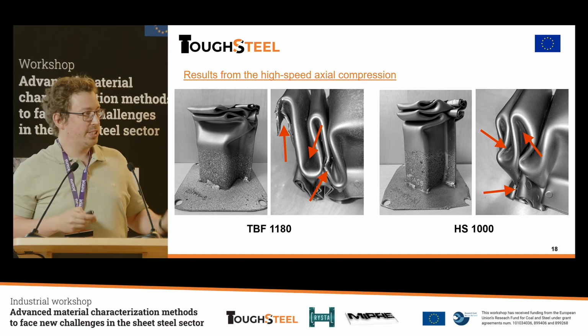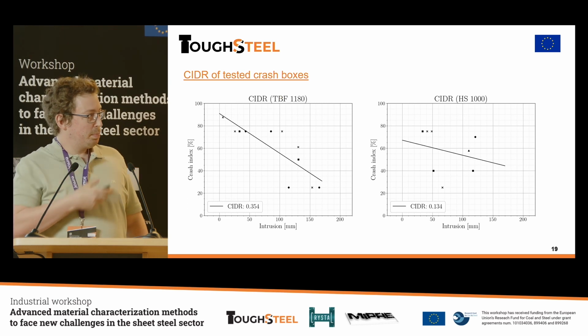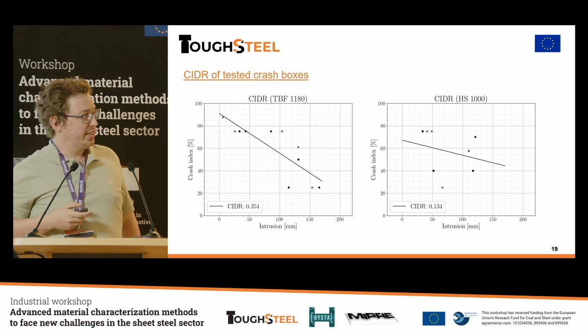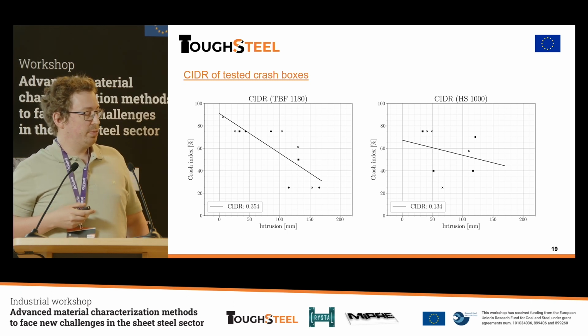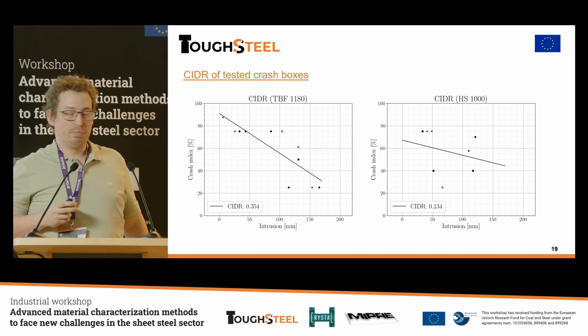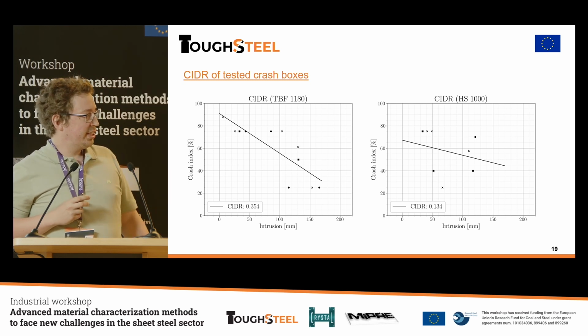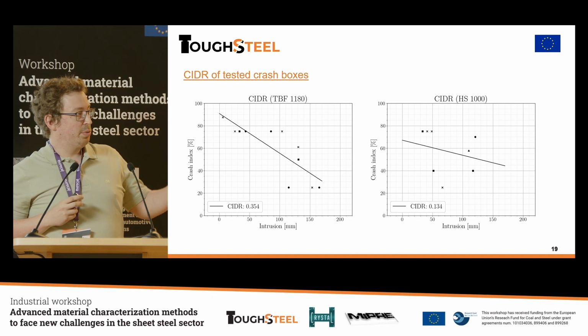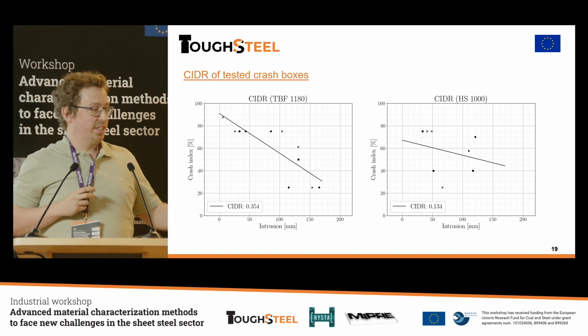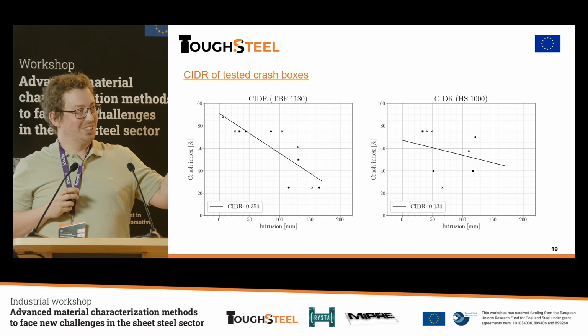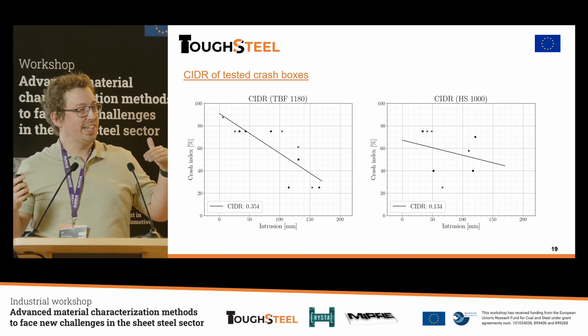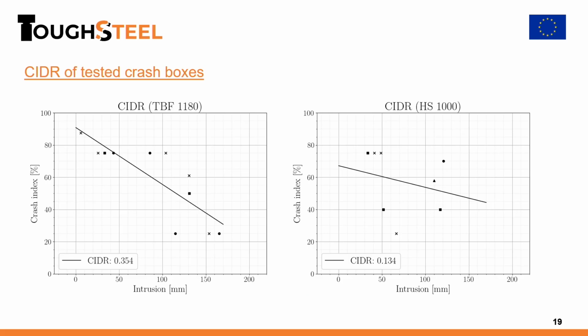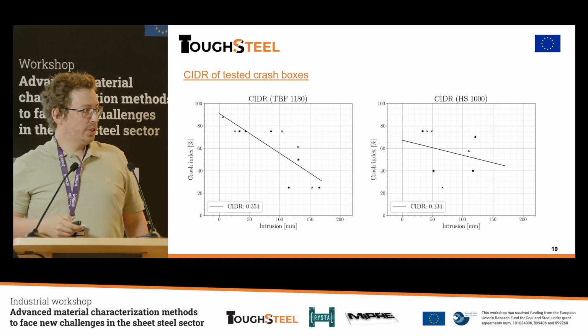It's a rough estimation. But basically what we received is the crash index decreasing rate here. And it was easier for the TBF material because we could see the cracks and we could measure them pretty well. And we can see that the crash index decreasing rate was a little bit higher than for the hot stamping grade. And I know the linear fit here is a stretch, but it was the best we could do. But the trend is clear. We can see that, as we could expect from the essential work of fracture values as well, the crash resistance is better for the right one, the hot stamping steel.